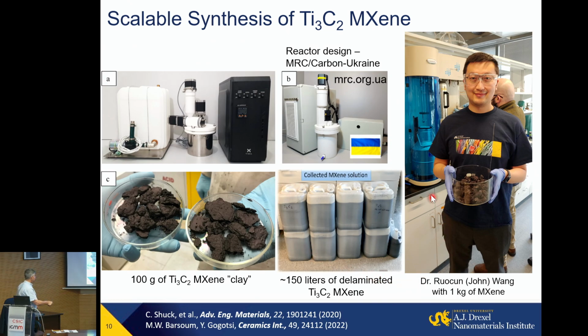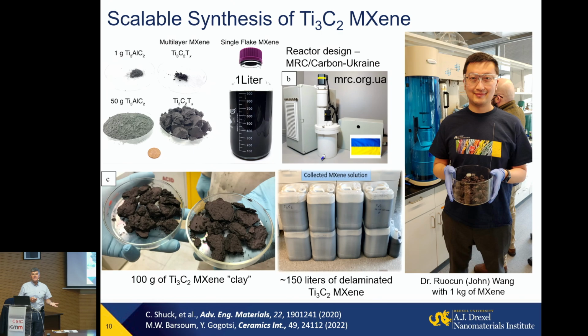And after that, you can disperse it, and you can see, for example, here about 150 liters of delaminated titanium carbide MXene in these 5-gallon containers standing here. And this is my postdoc, John Wang. He's actually joining the University of Texas, Dallas as faculty in August. He is holding 1 kilogram of MXene, which was produced within 24 hours in our lab. So again, it opens opportunity for large-scale applications.